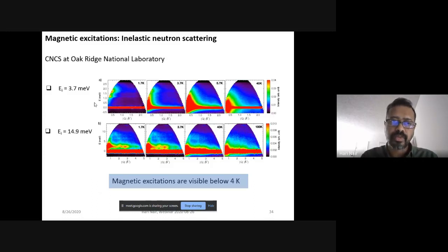We do that for our compound, and you see these nice color maps. There are two sets of color maps. The first row of color maps, each of them is measured at a different temperature. So 1.7, 3.7, 5.7, and 40. They are all measured at a single incoming energy of 3.7 meV, milli electron volt, for the neutron. And the color map shows the intensity. Wherever you see a color of red or orange, there is very high intensity. And wherever you see blue or purple, you have very low intensity.